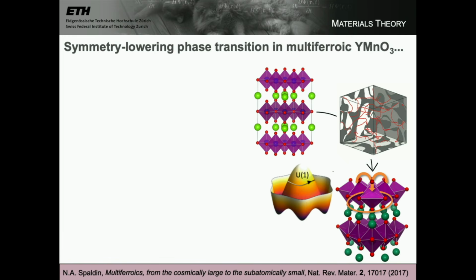Mathematically, we describe this process by a potential which has the form of a Mexican hat. So this potential is showing energy as a function of magnitude of the distortion coming away from the peak of the hat and angle of the distortion as I go around the brim. And this is not a cartoon. This is actually mathematically, when we calculate this process, this is mathematically what the energy surface looks like.